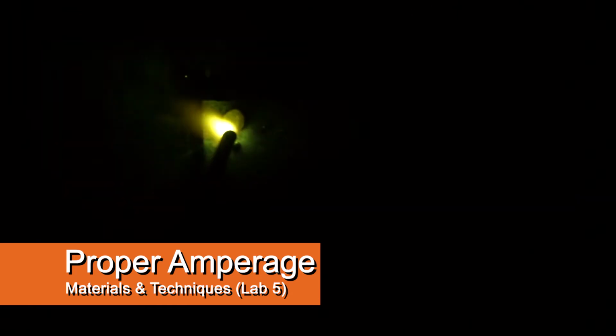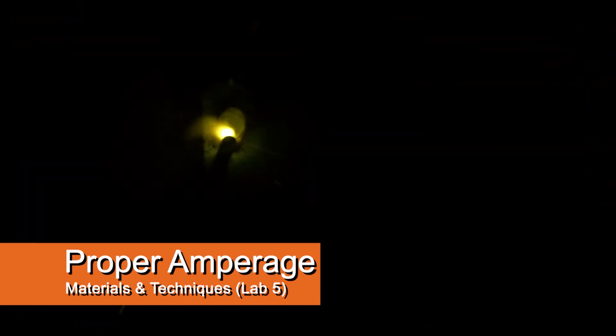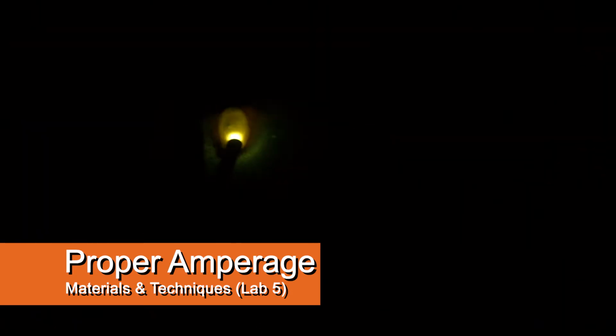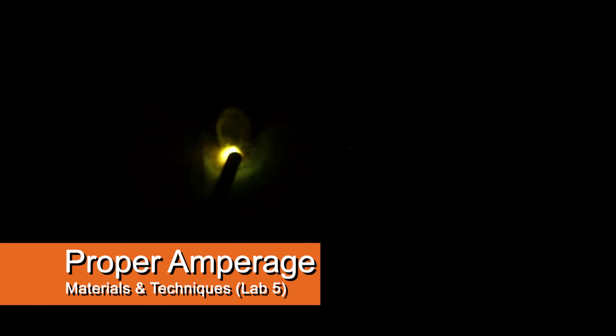Proper amperage is essential to all forms of welding. If the amperage is too low, as shown, it will be difficult to keep the arc up for any period of time. A low amperage like this also has very low penetration, which makes for a bad weld. The correct amperage you should be running in this lab should be around 120 to 135 amps as shown. 135 amps gives us good penetration while also minimizing the amount of spatter we have.